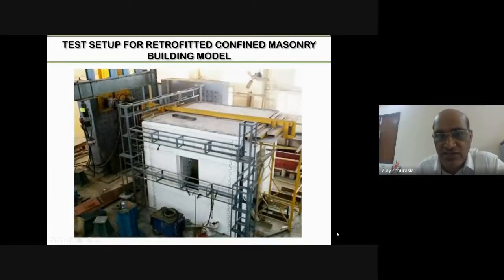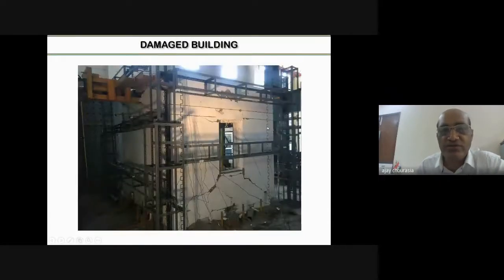In this, you can see we have painted it white to have a clear view of the cracks happening. Here is the actuator which is applying the displacement-controlled lateral load at the roof level, because the inertia force is acting at the roof level. The single point load coming from the actuator was divided into 8 different locations by a specially designed grid-type loading frame at one end, and a similar system was provided on the other, connected at the bottom and top together to incorporate reverse cyclic loading under displacement control at the roof level on this retrofitted masonry building model. With this incremental increase in displacement-controlled loading, it was tested up to failure but not total collapse.